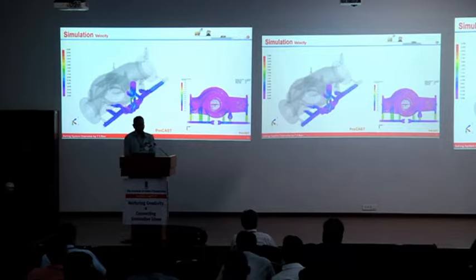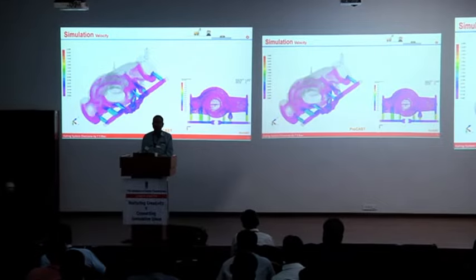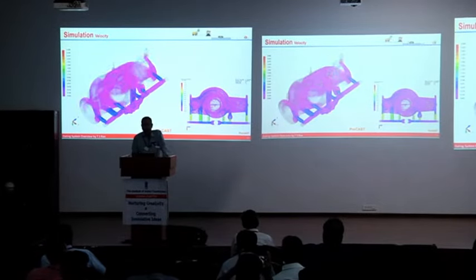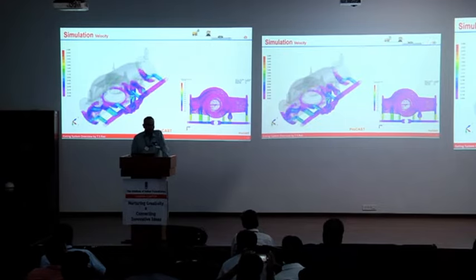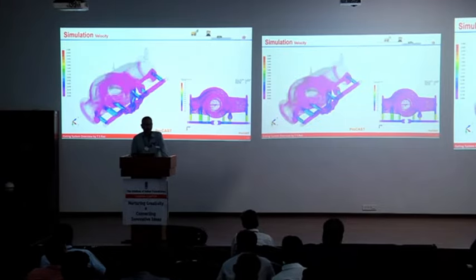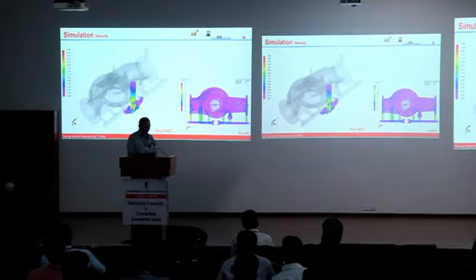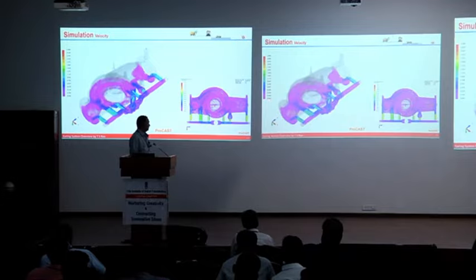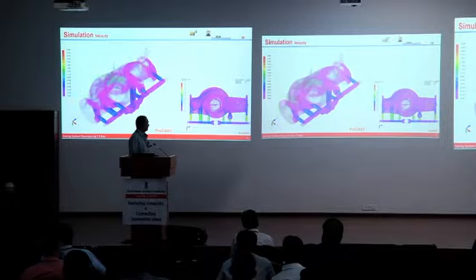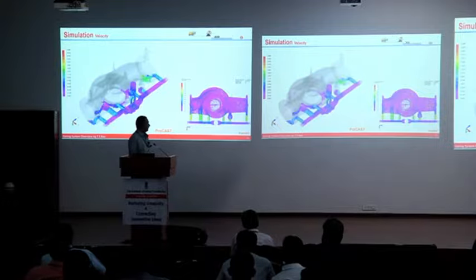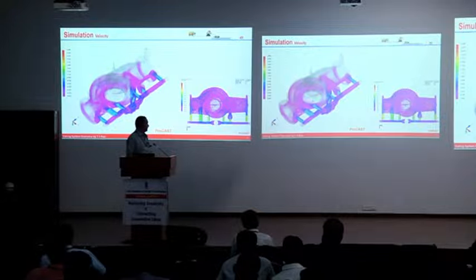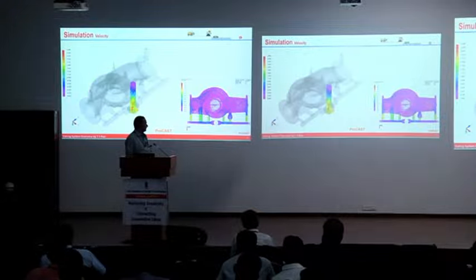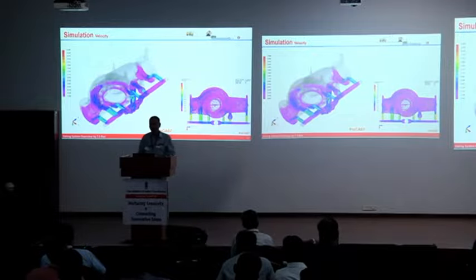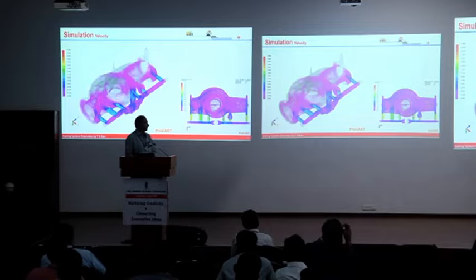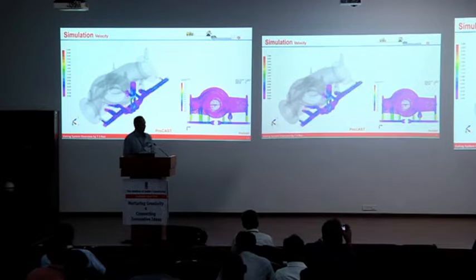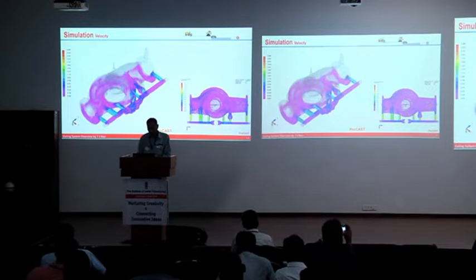So the next one is on the velocity. Velocity is very important with respect to the casting quality. The higher the velocity, the higher the turbulence in the mold cavity, and the higher the inclusions in the casting. The velocity can be defined by the graphical form here, this color being 0 and this color being 2. Any velocity beyond 1.5 is dangerous. Normally you see the higher velocities in the ingates, because these are the chokes. We can also identify where the choke is in the whole gating system. The velocity is important with respect to having a sound casting and filling time.